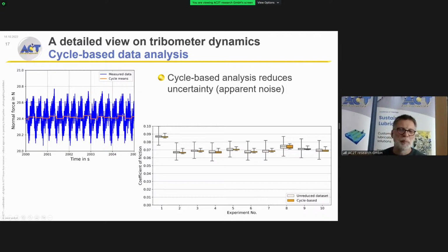We have an example where we repeated the same experiment 10 times. We see that we get quite reproducible values for the coefficient of friction. And what is sketched in the left graph is that the blue data, the raw data, are actually comprised of a cycle average and a periodic signal. If you remove the periodic signal, then the noise gets reduced dramatically.